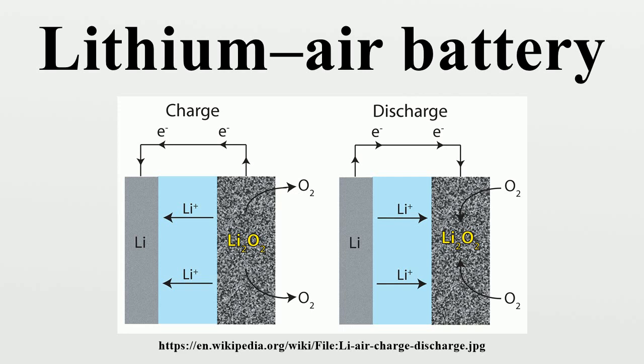Under some circumstances, manganese-catalyzed cathodes performed best, with a specific capacity of 3137 mAh per gram. Carbon and cobalt-catalyzed cathodes performed second best, with a specific capacity of 2414 mAh per gram. Based on the first pore-scale modeling of lithium-air batteries, the microstructure of the cathode significantly affects battery capacity in both non-pore blocking and pore blocking regimes.